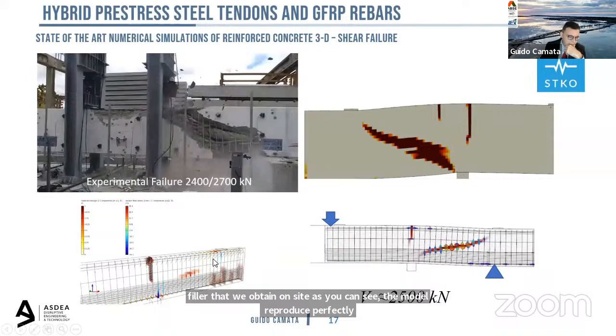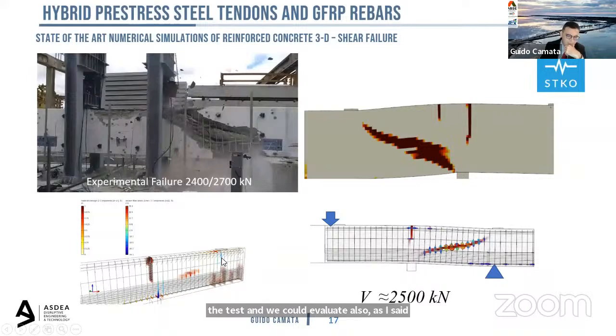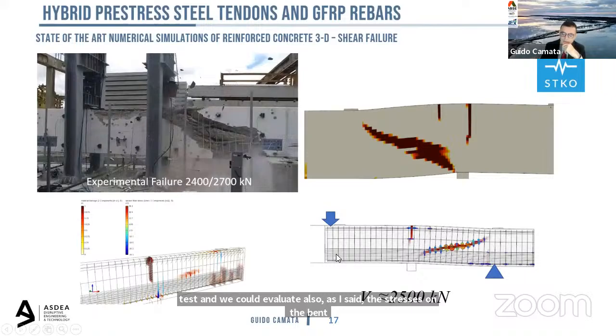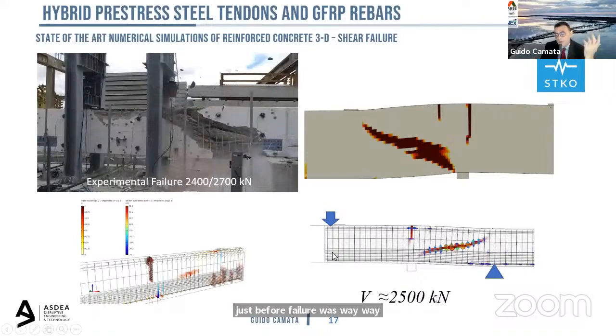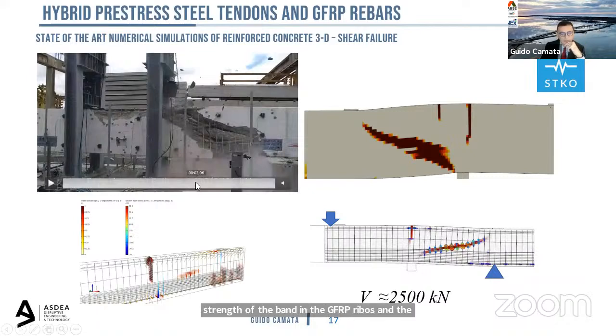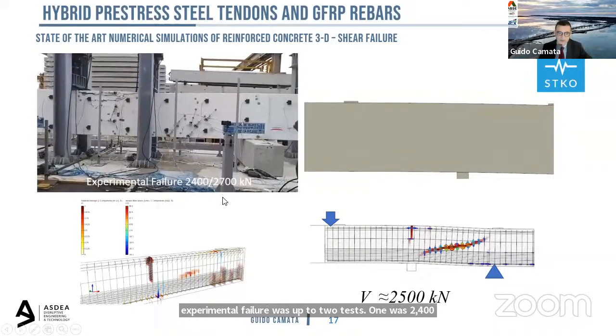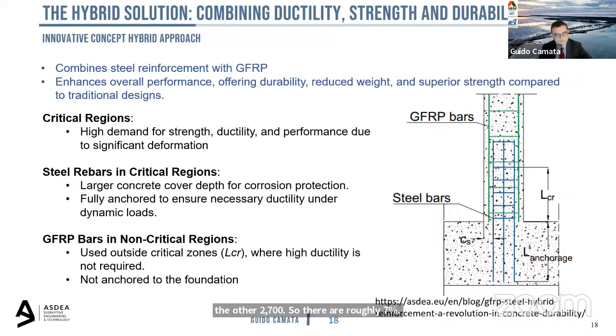And we could evaluate also, as I said, the stresses on the band just before failure was way below the allowable strength of the band in the GFRP rebars. And the experimental failure was up to 2 tests. One was 2,400, the other 2,700. So the error was roughly 7%. So the models work very well to model this kind of structures.